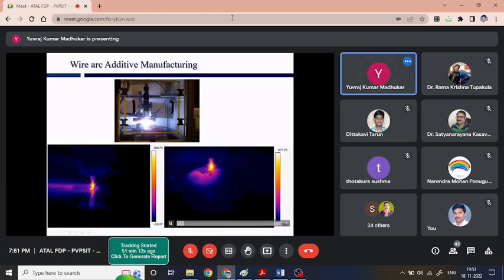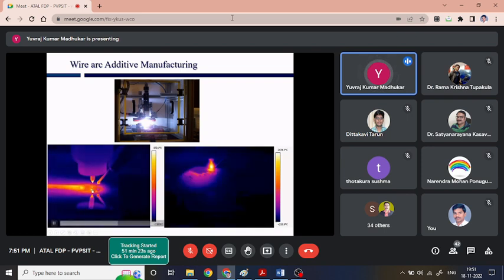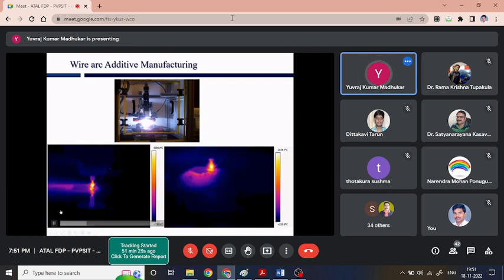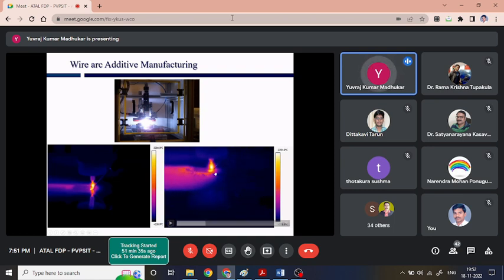Now, this is the first layer of the deposition, and this is the 11th or 12th layer, I think, or the 10th layer of the deposition. One thing we have to notice: when we are depositing the first layer, the melt pool size is very small. We can see the melt pool size is very small compared to when we are depositing the 10th layer, where the melt pool size is significantly larger.